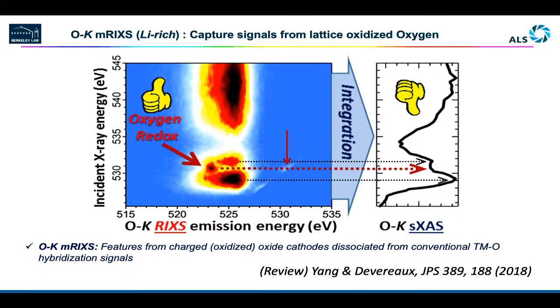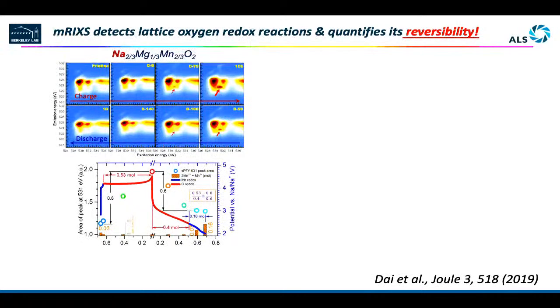But in the meantime, if we pull out the RIXS map of this transition metal oxide in a famous compound, I will come to what this means also. But it's in a compound where we know there is oxidized oxygen. And then you will see some individual features close to the elastic peak and also a very strong island of signal around 531 excitation energy over there. And in the integration of X-ray absorption, you typically see, depending on what kind of transition metal, sometimes a peak. In this case, I intentionally chose this material, you just see a value. You don't really see the signature in the X-ray absorption pre-edge again. So this is one of the features we really want to see.